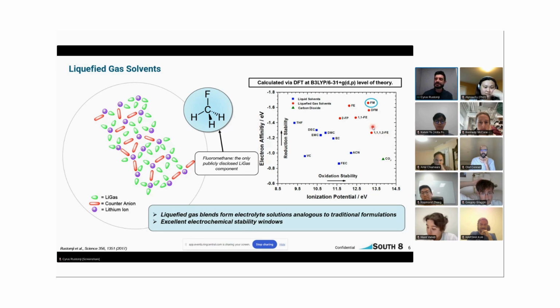Pretty much the idea here is to move to the upper right section of this chart. The more to the upper right you go, the more stable that solvent is electrochemically, and it can perform a better cycle life than you would if you were less stable. Now, of course, you want to form stable SEIs and CEIs, and that kind of comes into a lot of the tricks that we do here at South 8, of course.